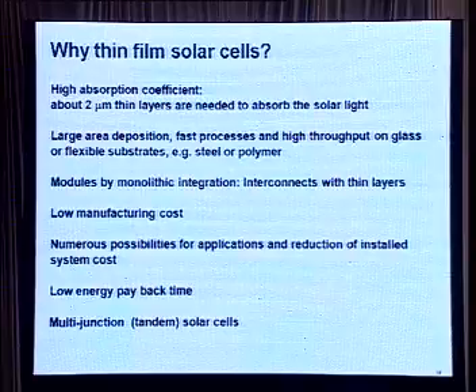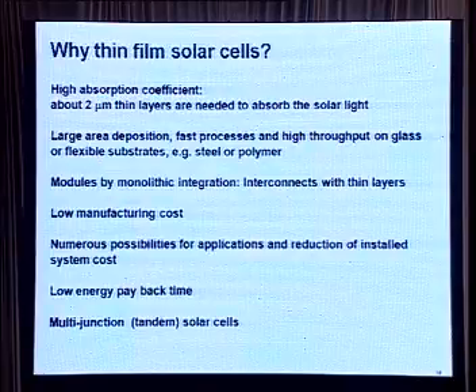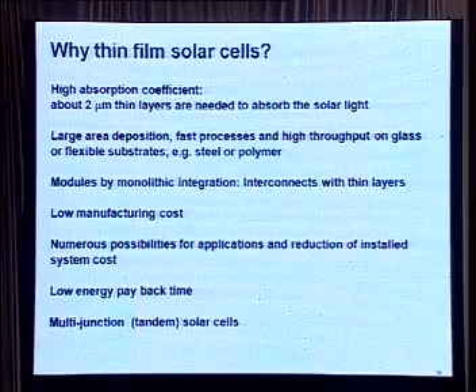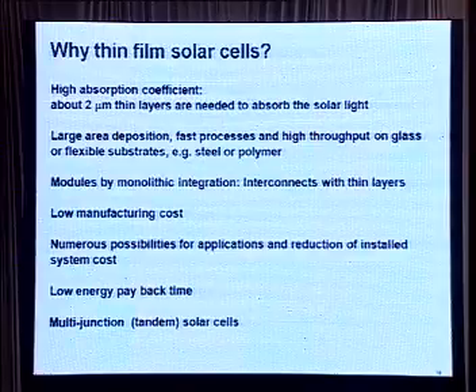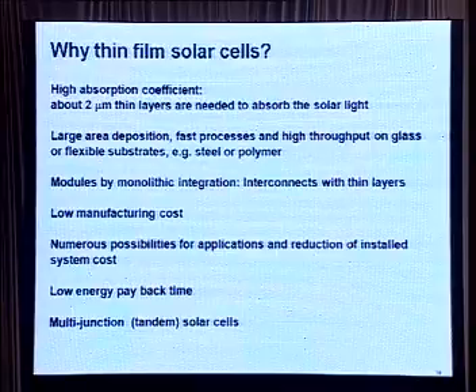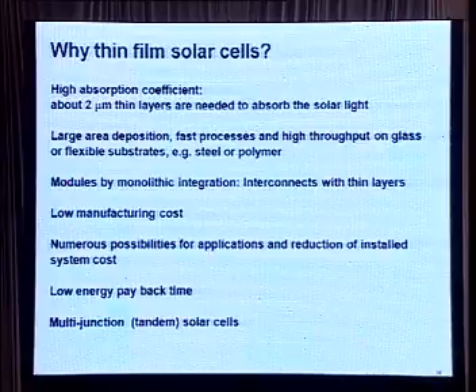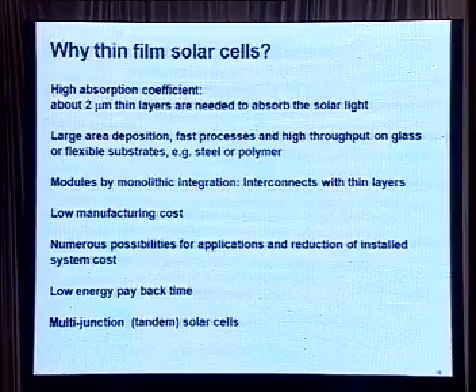First of all, in case of crystalline silicon wafers, one requires roughly about 200 micron thick material because it has a very low absorption coefficient. When we use thin film materials, they have very high absorption coefficient, so roughly 1 or 2 micron material, almost 100 times thinner material, is adequate to absorb all the light which we want to convert into electricity. Then one can have these coatings on glass or on steel or polymer films, and one can make monolithic interconnect modules, and I'll show you what it means.